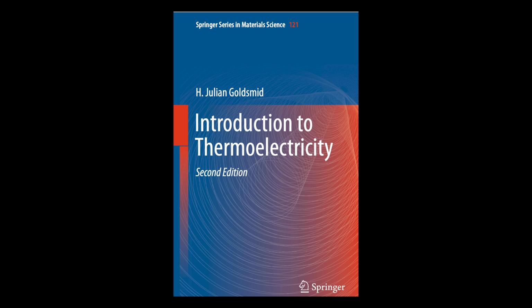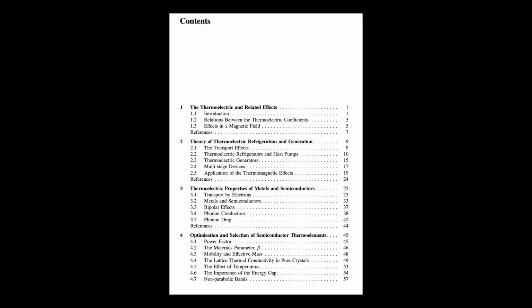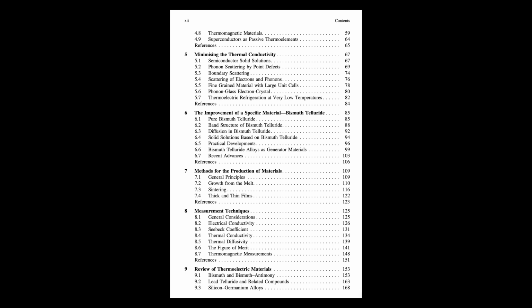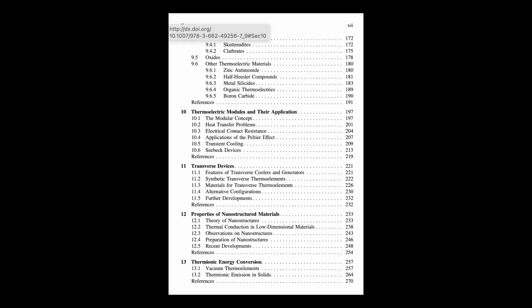Clever variations use Peltier elements to generate the wave, or even use the sample's own Seebeck effect to detect the temperature oscillations. Cool. And the figure of merit, ZT itself, can we measure that directly? Yes, there's a Harman method designed specifically for direct ZT measurement. You measure the sample's electrical resistance twice, once under near adiabatic conditions, no heat exchange, once under isothermal conditions, constant temperature. The ratio of these two resistances is directly related to ZT. You might suspend the sample in vacuum, adiabatic, or clamp one end to a big heat sink, isothermal. Still need to be careful about heat losses through leads, etc., but it's a direct way to get ZT. It can also give you contact resistance info.